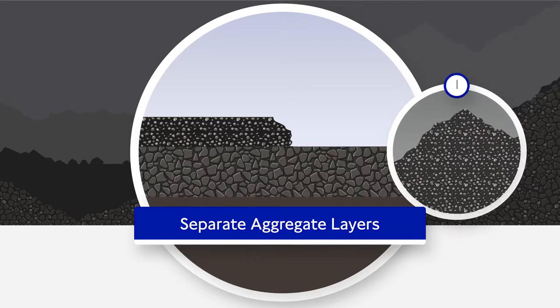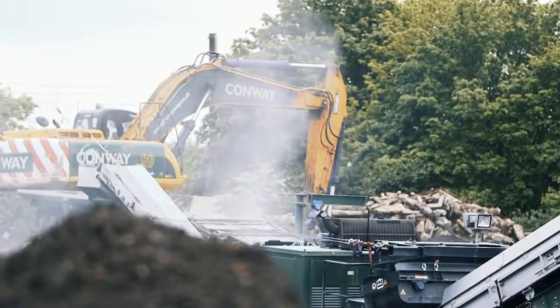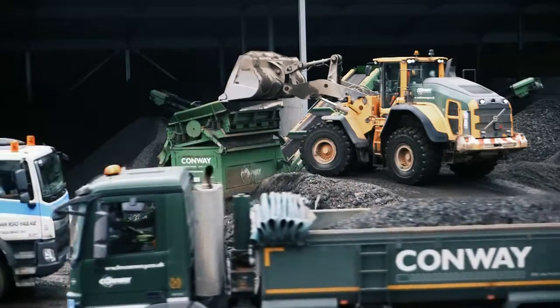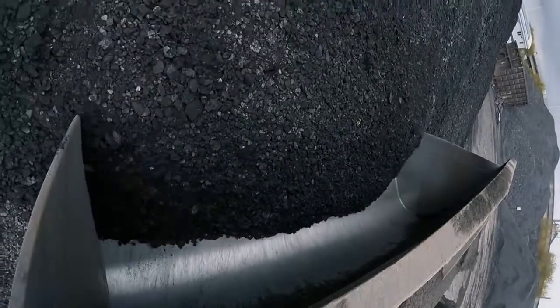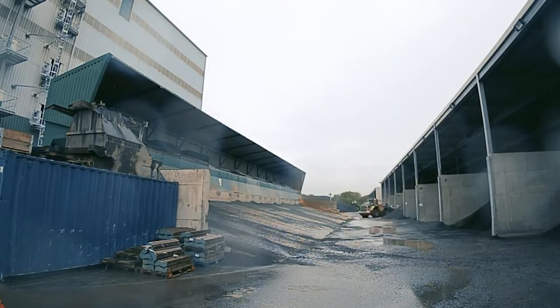It introduces an additional operation in the removal of the road. Rather than taking up one whole layer with mixed aggregates, we are trying to separate — taking one layer and then another layer. This produces value because you can now segregate all the good quality aggregate and produce an asphalt. The recycled material is replacing both the bitumen and the aggregate, with 50% of the virgin mix's bitumen and aggregate replaced by recycled material. That's added in the top dryer, put in at a very high addition, preheated, which allows it to be used.